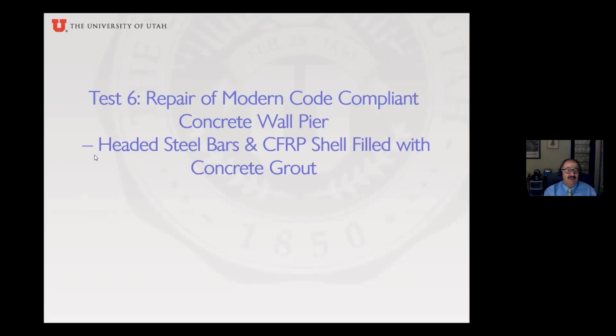So what it is, you forget about everything inside the wall, all the vertical steel, and you try to replace it with headed steel bars outside the concrete of the wall. And then you make a carbon fiber shell and you fill it with concrete grout. It's as simple as that. What you're doing is, all the damaged area in the plastic hinge on the bottom, you try actually to fill it with concrete and vertical steel bars that will transfer the tension to the wall that's not damaged, and you're moving the plastic hinge right above the donut.